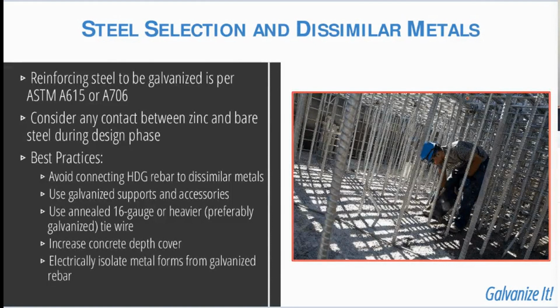Another design consideration would be to look at any contact with dissimilar metals, such as bare steel or stainless steel, or a combination of other rebar materials in the concrete. Best practices include the use of an all galvanized solution, including supports and any accessory items such as tie wires. You can also utilize dielectric tapes to insulate materials where dissimilar metals will be involved, or you can look at other alternatives such as increasing concrete cover to slow the rate at which the chlorides are able to build up in the concrete over time.